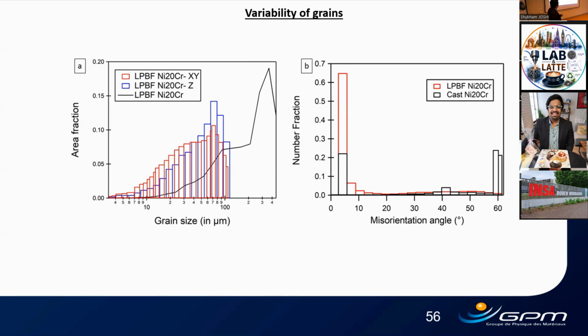Okay, and for the grain size? For the grain size, we have considered EBSD analysis. I will just show here. For the grain size analysis, we use EBSD analysis and we see the maximum area fraction. We choose an average grain size. So you use the equivalent diameter to estimate the grain size from the EBSD? Which method do you use? You have different methods to determine the grain size from the EBSD data. Did you consider the surface of the grain and calculate the equivalent diameter? No, we directly took the information from the EBSD analysis, maximum area fraction versus grain size, and we took an average. So yes, we clearly have variability of grain size in the model, but we went with the average size to at least have first foundations of the model.